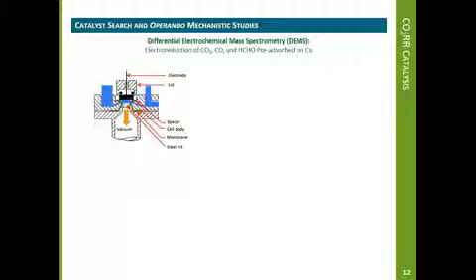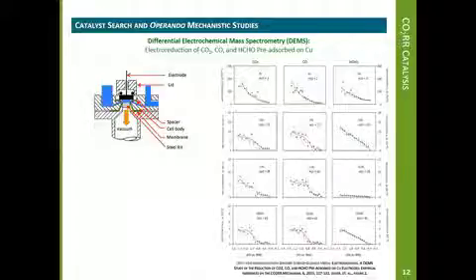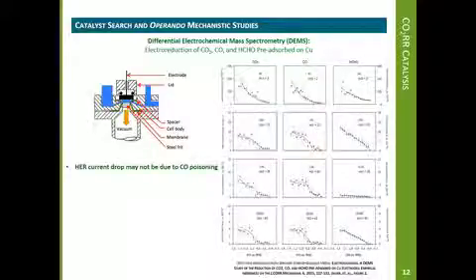Differential electrochemical mass spectrometry, or DEMS, provides operando analysis of gaseous and volatile products during an electrochemical scan. Results show that the initial decrease of HER current during CO2RR is not due to CO poisoning because the same current drop is also observed from pre-adsorbed formaldehyde where CO is not a reduction product.